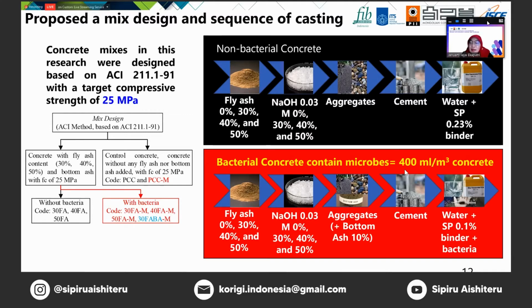because we keep the bacteria inside the concrete constant at about 400 milliliters per cubic meter of concrete. Because of the different workability using bacterial and non-bacterial concrete, we make a different content of superplasticizer. For non-bacterial concrete, we put 0.23 by binder weight, and we decrease the amount of the superplasticizer to only 0.1% by binder weight.